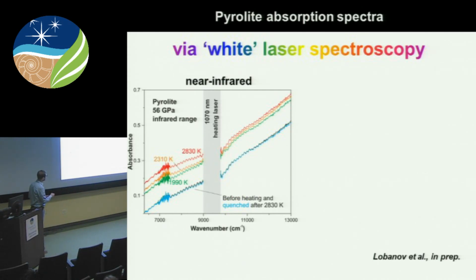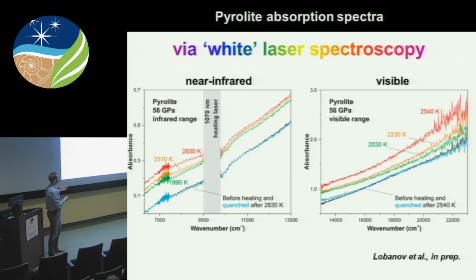So we, however, are not restricted to doing measurements on just minerals. We can do measurements on rocks. And here I'm showing you absorption spectra of pyrolite, which is a hypothetical rock that we think the mantle is made of. So here we're looking at the near-infrared range. The blue and black spectra are before and after heating. They look exactly the same, which is something you always want to have. And then you can see that at high temperature, the absorbance of this sample is very different. So the sample is much darker at high temperature.